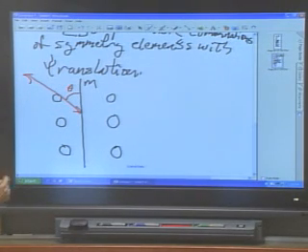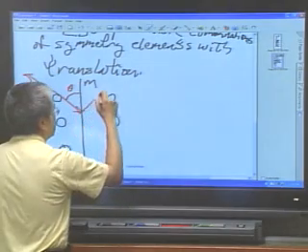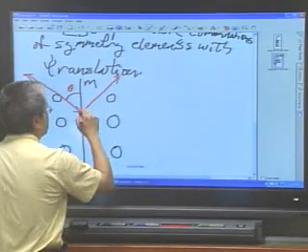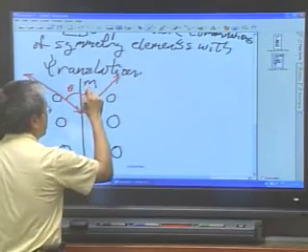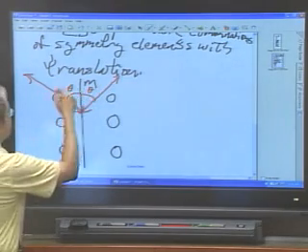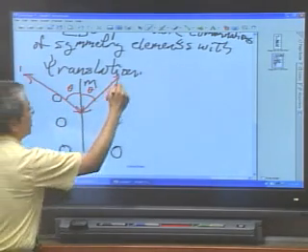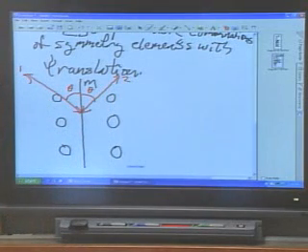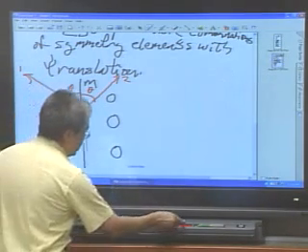Now, suppose you measure the property in this direction, where this direction is also at the angle theta with respect to the mirror plane. It's just the mirror operation of this direction. I would argue that the property in this direction, let's call this direction 1, and the property in this direction 2 should be the same. That is, they're equivalent.